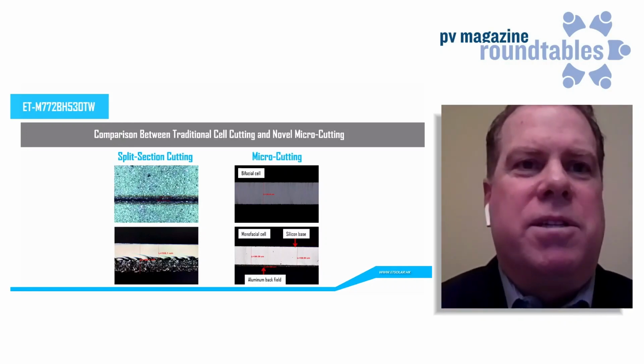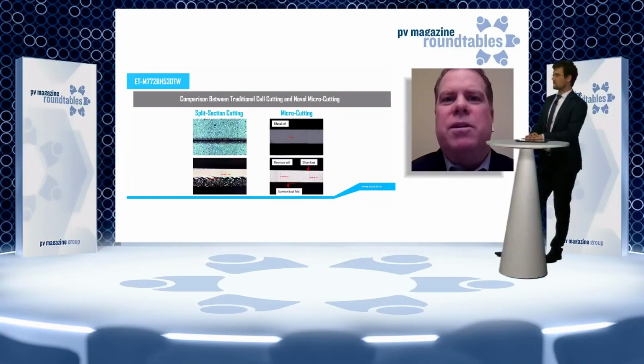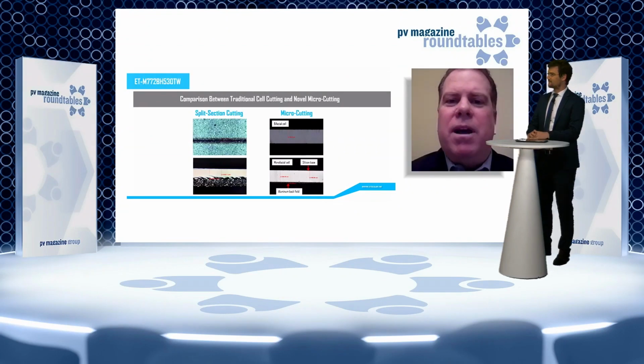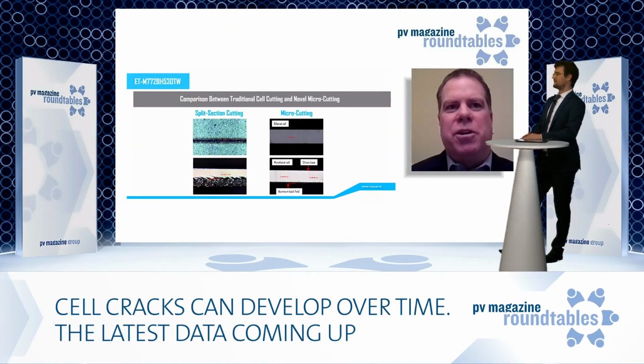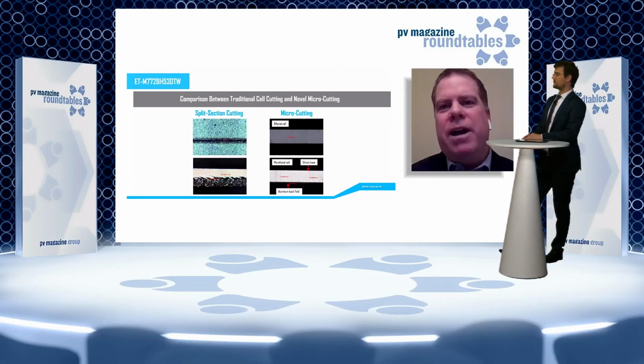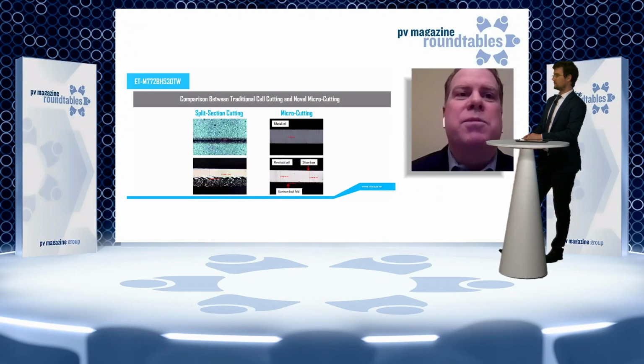And one important note here is, as ET Solar has opted to employ the 180 millimeter format. Some module manufacturers are utilizing a larger format, the G12, 210 millimeters, or even beyond. And those processes that are associated with those larger format cells don't just require a half-cut cell, but they are moving towards a cell being broken into thirds, which requires 2 cuts. And this would mean that there are some inconsistencies in the process where at least one of the 3 remaining cells from that process will have cuts on both sides.